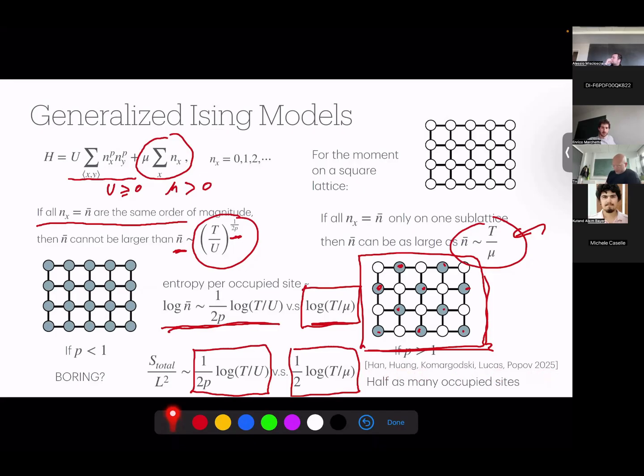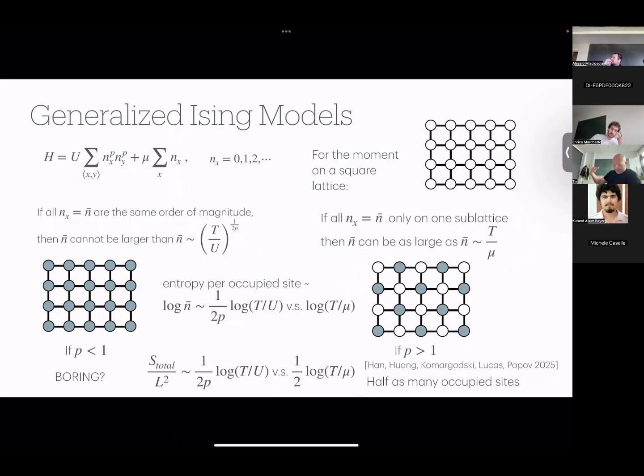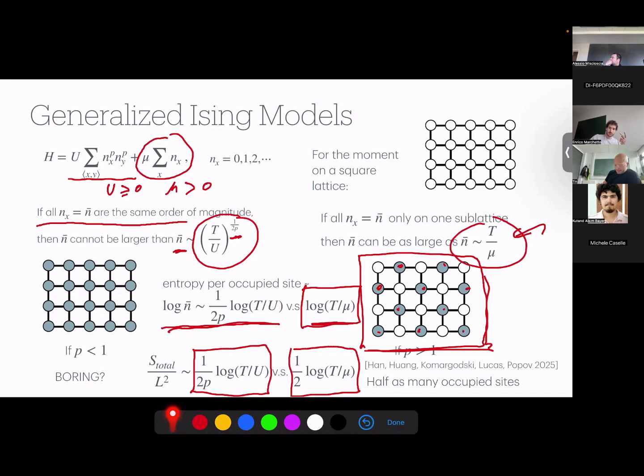That was the motivation for all of these models. So the point is that if this exponent p, or this repulsive interaction, is strongly repulsive enough, then we will always have order at high temperature, and repulsive enough means that p is strictly greater than 1. Whereas if p is less than 1, we have a boring case where gas dominates.